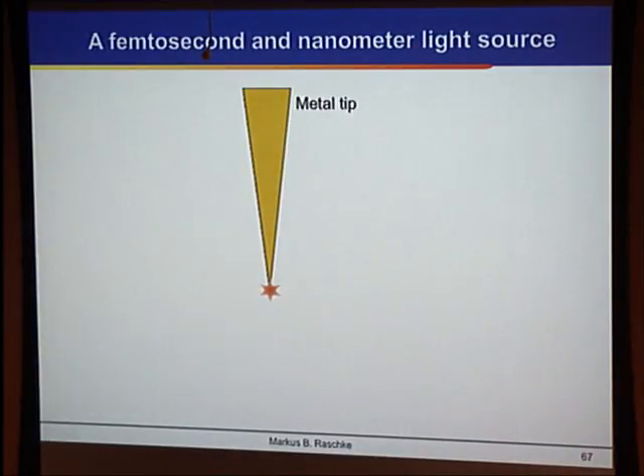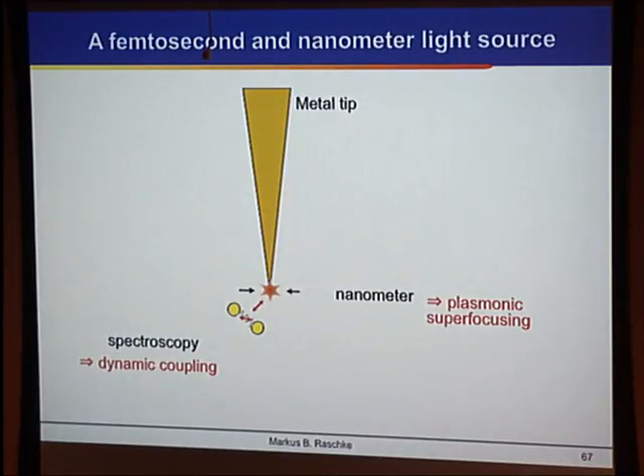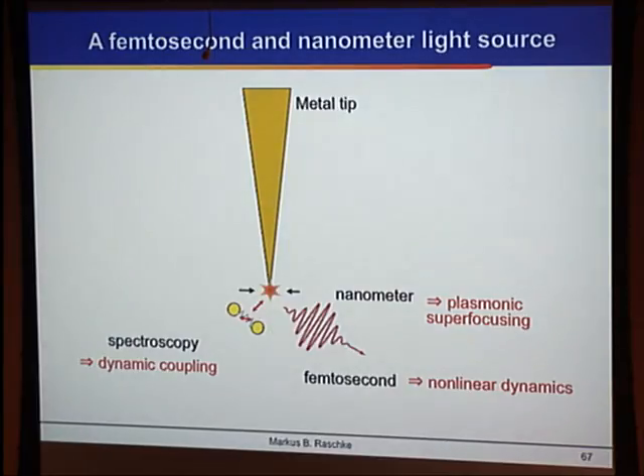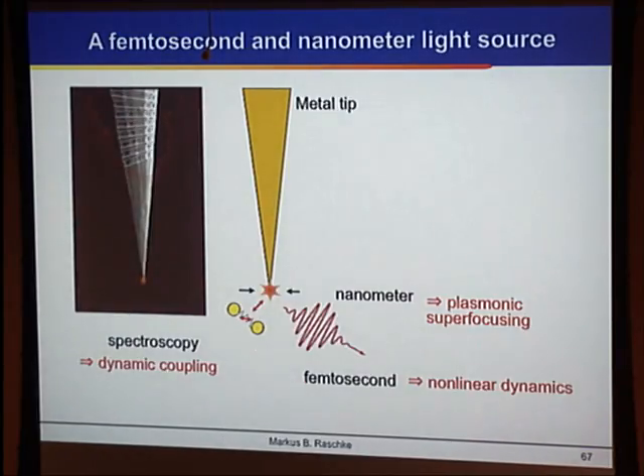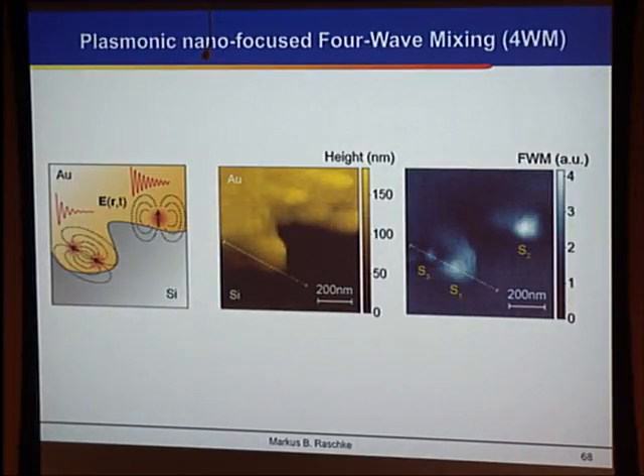And so for this, this was also many years in the making. We really conceived this tool where we wanted to have a femtosecond pulse confined at the apex for spectroscopy, appropriately spatially confined, and then with control on the single cycle limit. And it turns out that this tool exists in the form of the idea of adiabatic focusing, where we can launch a propagating surface wave on the tip shaft, which then compresses into this apex field. And I won't talk much about the details of this tool, but just show you that we can use that femtosecond localized light source in four-wave mixing to image, in this case, at a gold metal edge, the coupled plasmon dynamics in real space and time.